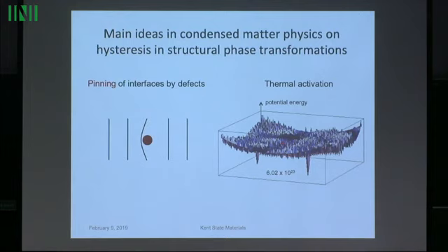It might even sit on average, not in a valley, but on the top of a mountain. That would be called entropically stabilized austenite. So it could be sitting on top of a mountain on average here. In any case, you start now lowering the temperature, and you can think of controlling, in the mathematical problem, the initial conditions. So you can start lowering the temperature, and eventually you fall back into this well, or one of these other wells associated with the martensite phase.